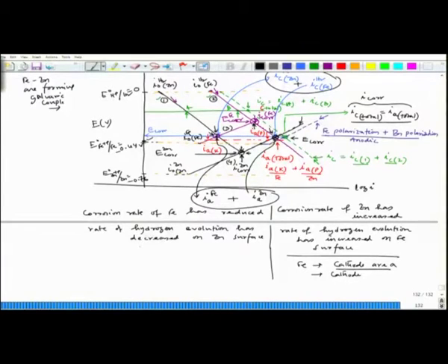And zinc dissolution has increased on the zinc surface. So zinc becomes the anodic area, or it will act as anode.